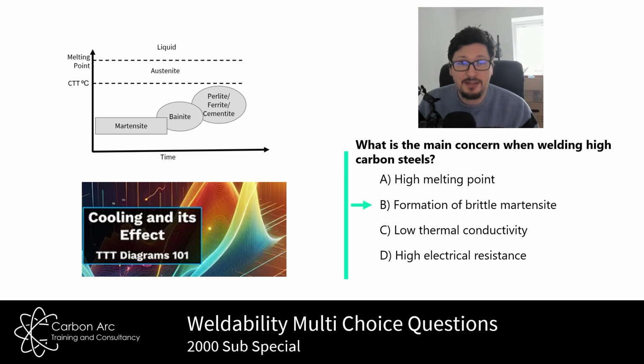But basically what happens here is, as carbon content increases within a material, the martensitic band of that TTT diagram will increase. It gets longer. It pushes the whole graph to the right. This means that for the same heat input, to try and get a pearlite, ferrite, cementite structure, good grain structure, we're going to need to have a much longer cooling time. Okay? So we will have to have a higher preheat value as we fall into that. So high strength carbon steels, generally high preheat values, slow cooling rates.